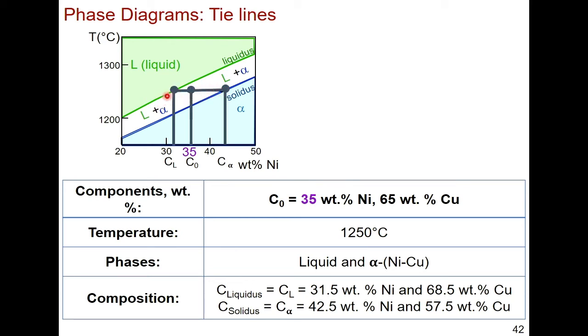Here it's 1250 C, here it's a little bit less than 1250 C, here it's getting closer to 1200 C. Okay? So you could see that that changes your tie line. That changes the phase fraction of liquid to alpha, and thus it changes the amount, because where your tie line touches the liquidus and where it touches the solidus tells you what Cl is, the amount of nickel that's in your liquid phase, and C alpha, the amount of nickel that is in your solid alpha phase. Okay? So, any clarifying questions in regards to that? I've said the same thing a number of times in different ways, so hopefully it's sticking. Okay? But your C naught hasn't changed.